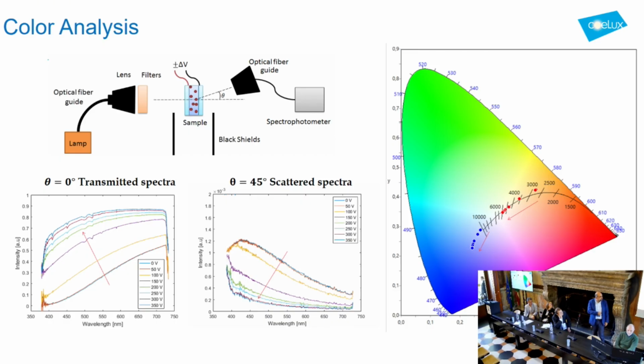If you increase the voltage, the transmitted spectrum goes from the long wavelengths, the red, toward more brightness. In contrast, the diffused light goes from a coarse bluish, more in the short wavelengths. As you increase the voltage, the scattering diminishes, of course, because we are matching the indices, but the dependence goes very steep, and we have the dip.